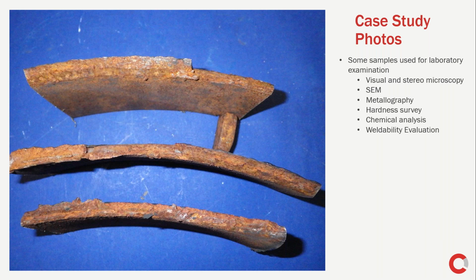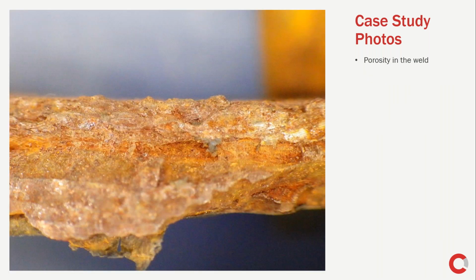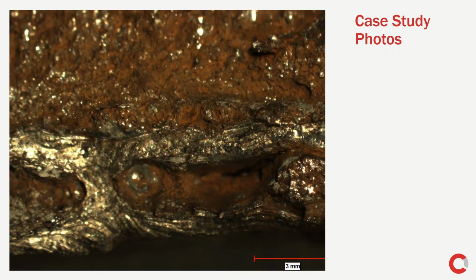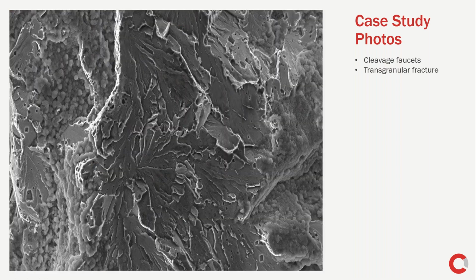These are a few samples that we selected for examination. Looking under the stereo microscope, we saw large voids in the weld. These are undesirable features because they act as stress concentrators and will diminish the load carrying capability of the weld. Further examination revealed not only large porosity, but also inclusions, which are also undesirable in a weld.